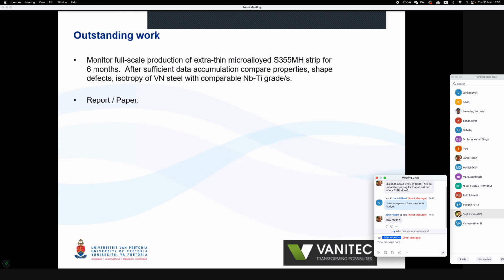I'll just finish. To be honest, we did detect a few pinch defects in this very thin steel, but not more frequent than has been experienced in niobium steels that were processed earlier.